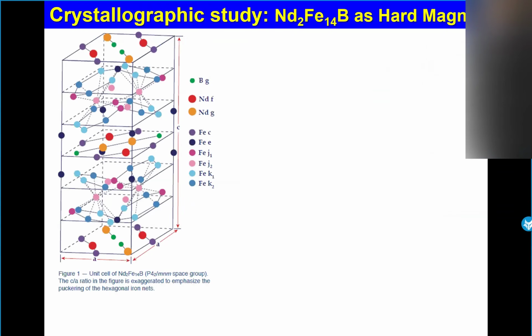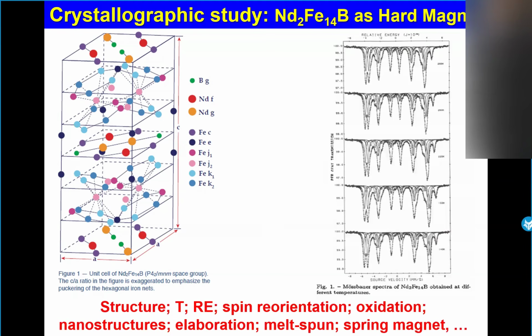Okay. So now if we consider this system, neodymium iron boron, so of course it's quite complex. There are 6 different iron sites. So of course, the Mössbauer spectra are very complex. Here you have a series versus temperature. So it was possible to fit, and the best fit corresponded well to the content of the different iron sites. That means 50-50, 25-25, and 12.5, 12.5.